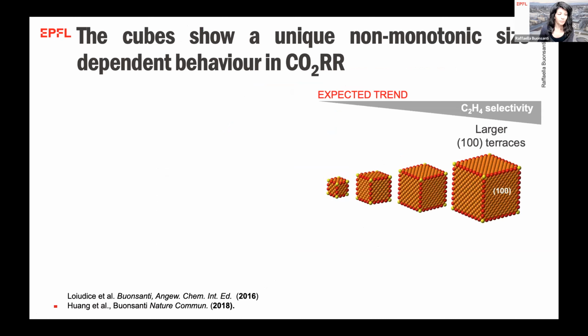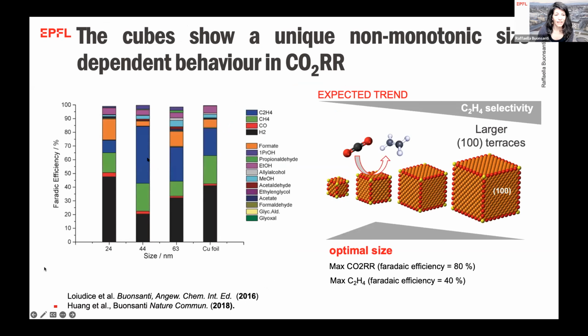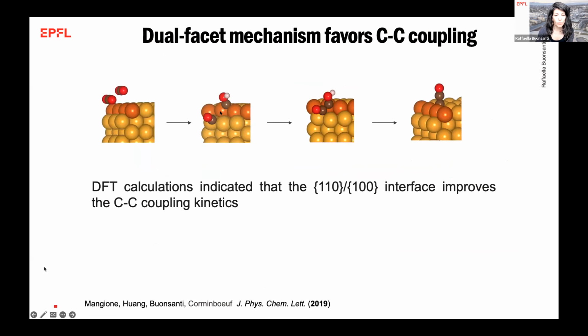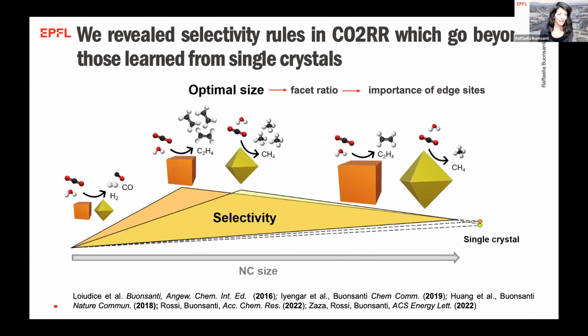However, we also understood something more. Indeed, based on the single crystal studies, we would have expected that the bigger cubes showed the highest selectivity for ethylene. However, this is not what we found, because we found that the intermediate size of the cubes was actually the most selective for ethylene. And we explained this by theory, which proposed the edges as the location where the C-C coupling needed for the ethylene formation occurs on cubes. So basically, these well-controlled copper nanocrystals allowed us not only to confirm some of the selectivity trends observed in single crystals, but actually to go beyond them, because we could identify an optimal size, which implicates the importance of edge sites.